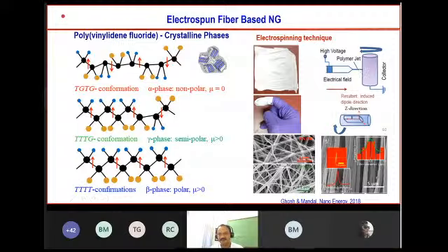polarity. We are applying the high electric field between the polymer jet and collector, and there is a gap here. And here we are giving the pressure. So once we apply the pressure, what happens? Without an electric field, the polymer solution will form a drop flow, right? But once we apply the electric field between the metallic collector and this metallic tip, then what happens? Instead of a drop, you will find a spray of polymer jet. This is known as the polymer jet.